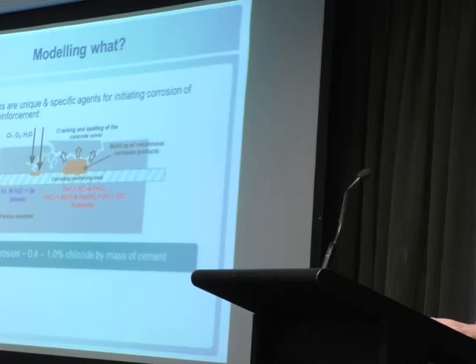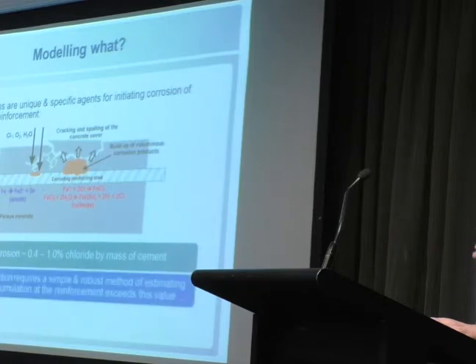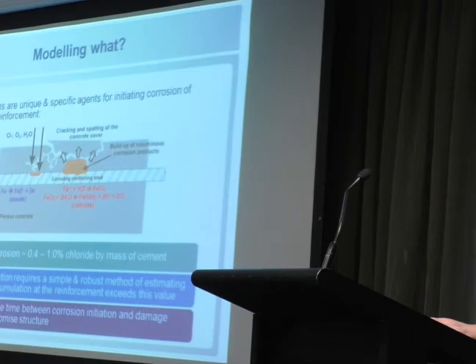But accepted wisdom is that chlorides are an aggressive agent that will cause corrosion of reinforcement, and they will penetrate through the cover concrete over time, and that there is some minimum threshold level, and we'll talk more about what that threshold level might be later, which initiates corrosion. So there's two things you can model, as you've already heard. You can model the initiation time, how long it'll take for the chloride concentration at the reinforcement to exceed that threshold, or you can go on and model the propagation time, how long it takes before some level of damage is sustained that reduces the structural capacity of your structure.